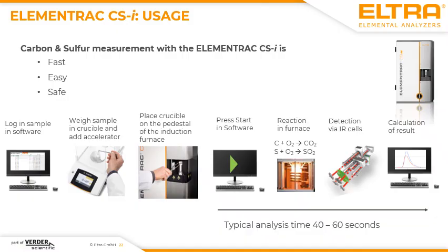It's also important to use the correct accelerator. For example, iron-based samples can just be processed with tungsten as accelerator, but some carbides or, for example, cast iron samples could require different accelerators. About this fact, we'll talk in the following. Placing the crucible with accelerator on the pedestal is not critical. It's also not critical to press start in the software.